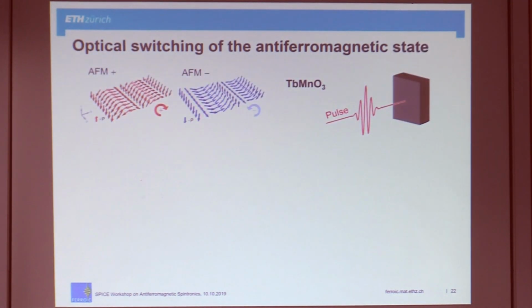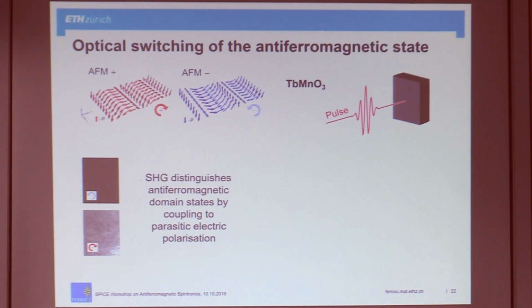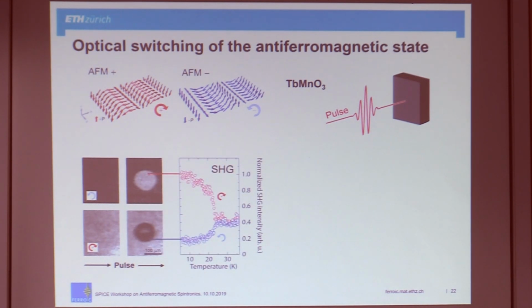OK, so now we take two samples, and we get them into a single domain state, which has either a left or a right-handed antiferromagnetic spin spiral. And we irradiate this sample with a strong light pulse. Here we have our single domain samples before we irradiate them. And after irradiation, it looks like this. Where the laser pulse has hit, you reverse the antiferromagnetization. You can see that you really look at the antiferromagnetic order because once you reach the Néel temperature, this splitting, this contrast, is gone.